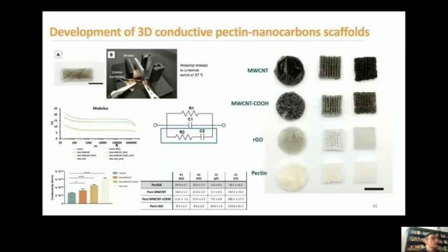On these films, we also tried to perform an electrical characterization in order to analyze what are the parameters that principally influence the electrical properties. And as you can see here from this graph, by increasing the quantity of carbon nanotubes or also the graphene, we are able to modulate the conductivity of the materials.